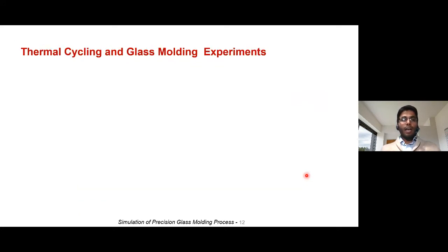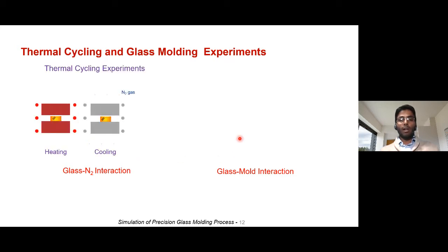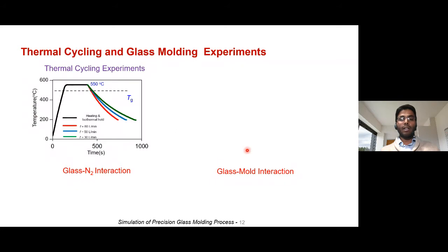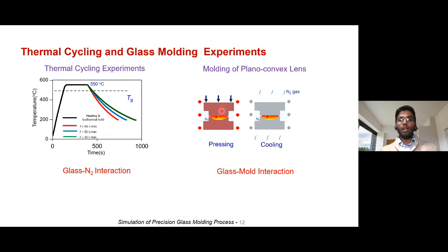In order to address these thermal boundary conditions, we planned two sets of experiments. One was a thermal cycling experiment, and the second was a glass molding experiment where we fabricated a lens. We tried to address the glass nitrogen interaction, how to model it, by the thermal cycling experiments, and we wanted to address the glass mold interaction by conducting a lens pressing operation. Here you see a plano-convex lens, which we have pressed against the molds.